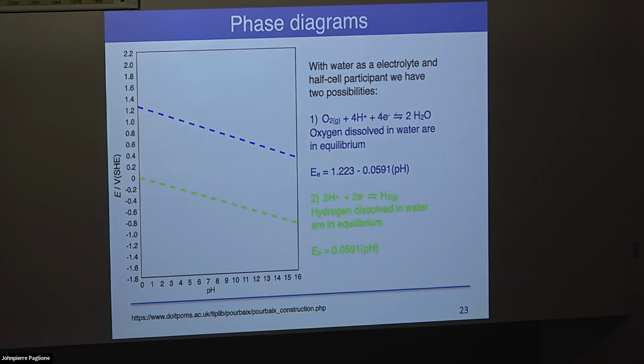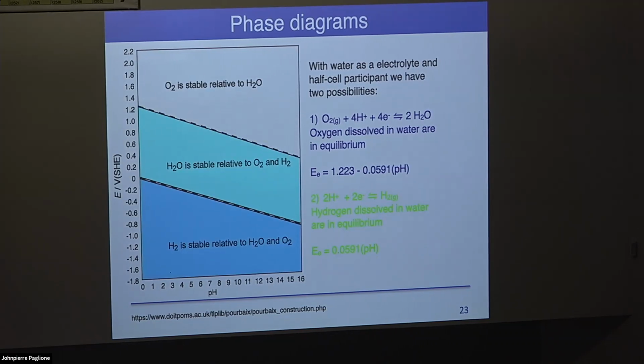Most Pourbaix diagrams, you'll see 2 dotted lines on them in the background, and those 2 dotted lines tell you something about the solvent you're using, so water. Basically, you have 2 half-cell reactions that you can have with water. Above the blue line, you have water being oxidized so that you have oxygen in equilibrium with water in the solution. In between these 2 regimes, water is stable. Below this regime, you have water being reduced to hydrogen gas in equilibrium with water. So that shows you the 2 different regimes you have.